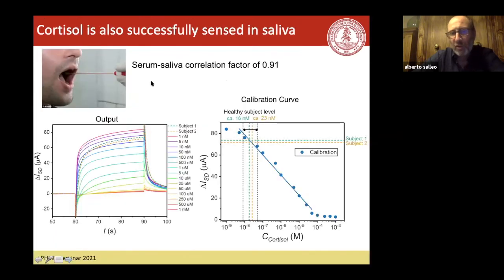It turns out you can measure it also in other fluids. For example, people are also interested in measuring cortisol from saliva. I think the correlation factor with serum is quite high. So we also measured from saliva, collected saliva, and then measured cortisol from it. After the calibration curve, it turns out the subjects were in the healthy level. And again, this corresponded quite well to what we measured by ELISA.